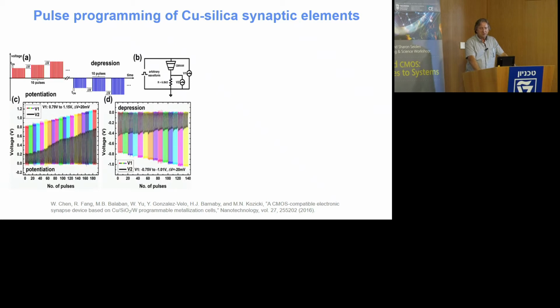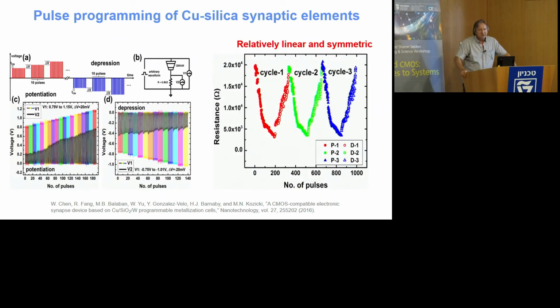So we looked at copper silica as a synapse, and we're actually quite surprised at how good the results were, looking at stimulating it with positive pulses and destimulating it with negative pulses, cutting to the chase here. One of the things that we saw is some relatively linear and relatively symmetric, what we call potentiation and depression in these things. Now, what's significant about that is most resistive systems, when you're training them, do not have particularly linear training ability. You tend to get curves that go up steeply and then they flatten off. In our copper silica elements, the potentiation depression was a fairly linear event, and just as delightfully, the symmetry that we got in the potentiation depression was also rather good over several cycles.